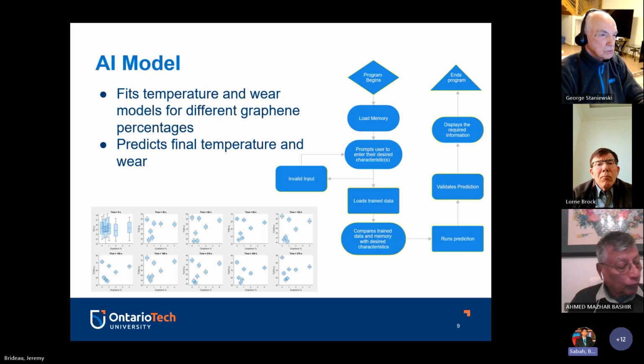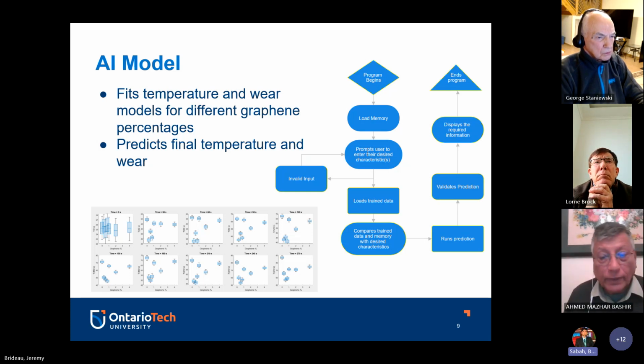I'm actually working on making an AI model that will predict graphene characteristics of different types of greases. So let's say, for example, you want to put 1% of graphene into this grease solution. I'll put it into the model prediction, and then it'll give you the predicted temperature based off of our ran simulations, the coefficient of friction at that point, as well as the wear scar and wear depth. And that's going to be extremely beneficial for companies who, let's say, are looking for 70 degrees, for example, as a temperature. So they're going to know exactly where to go.